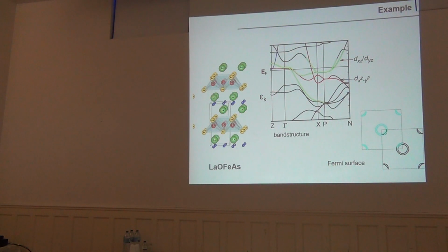With that, you get information about how your electronic structure looks, where in fact the electrons are mostly having transport, and you can start here now, if you want, to talk about, for instance, magnetism. What I did is I displaced this by a commensurate vector in the lattice, and I can fit perfectly the hole pockets to the electron pockets. And this is telling you the system has an instability towards magnetism.